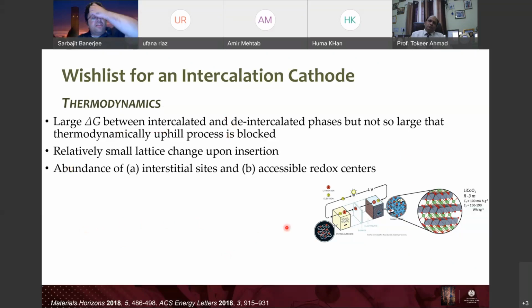Now, ideally, you want to have lithium ions entering the solid, and this intercalation or insertion reaction, which is reversible, should bring about a relatively small change in lattice volume, right? Again, this is important because if there are very large changes in lattice volume in this active element, that will result in lots of mechanical instability. This is especially true for all-solid-state batteries, but it's generally also true, and it is a leading cause of failure. I talked about the coupling with mechanics. These large volume changes will oftentimes result in substantial failure. A cathode material should have a high abundance of interstitial sites, so lots of areas to store the ions, because the ions have to go somewhere, right?